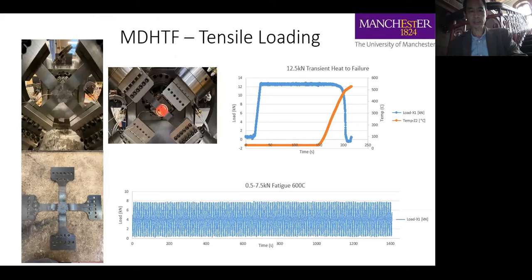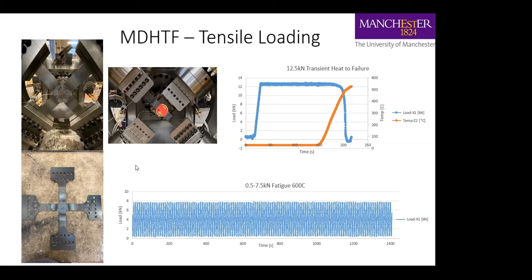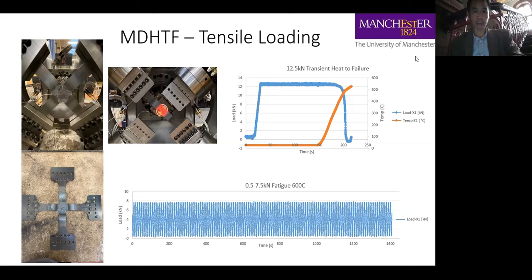And this is the tensile test. Again, you can see the red hot specimen in the machine, and in this case, we apply biaxial loading in 2 directions in any combination. This again can go up to 1,000 degrees, and the load is enough to fail the specimen in tension. In here, as in the compression test, if the 3rd surface is not covered, we have a digital imaging camera to look at the surface so that we can acquire data in much greater detail.